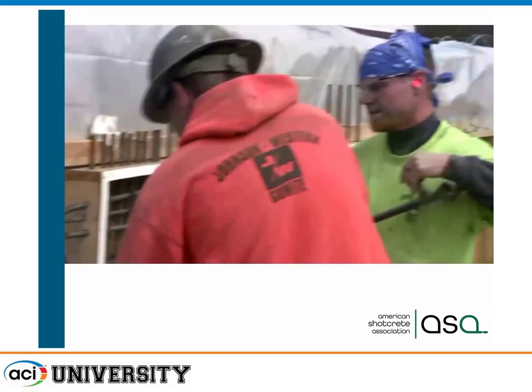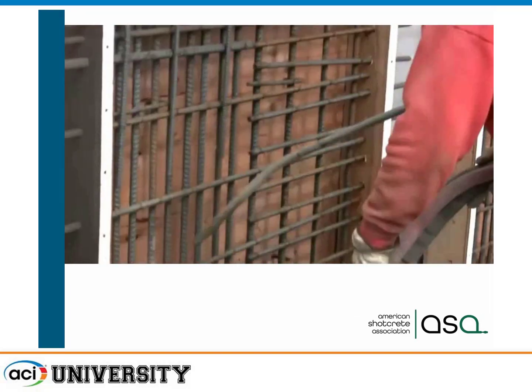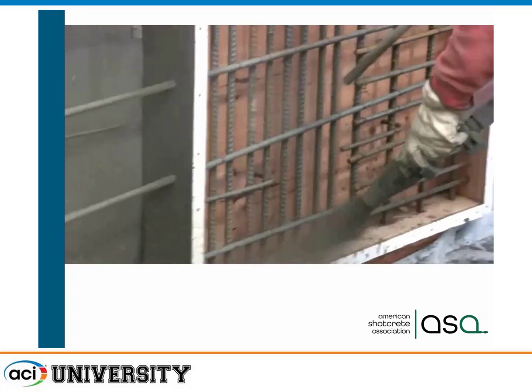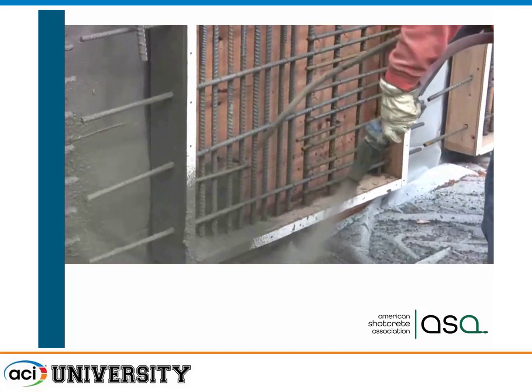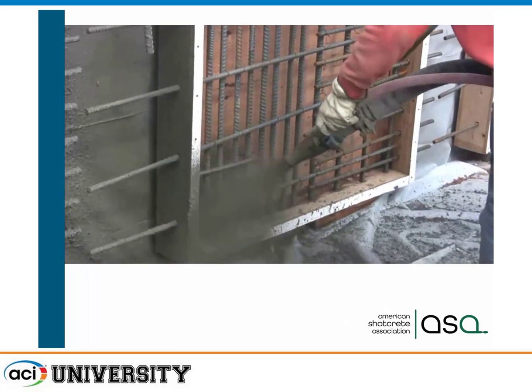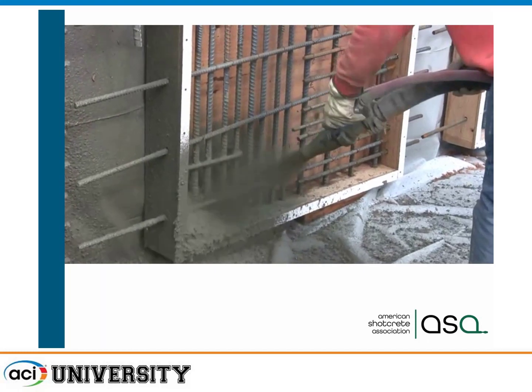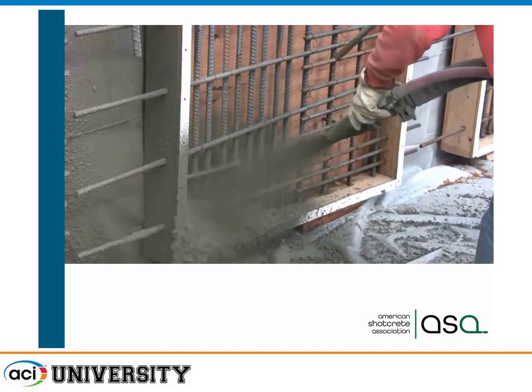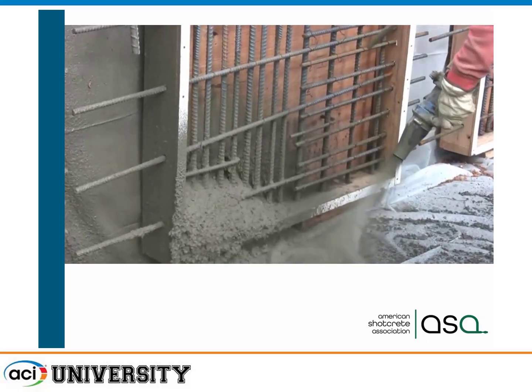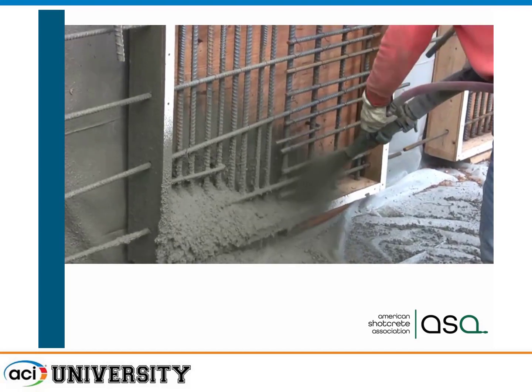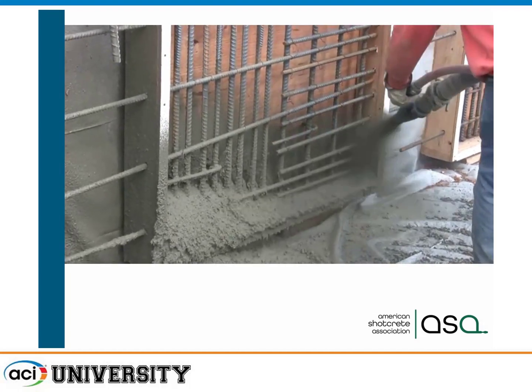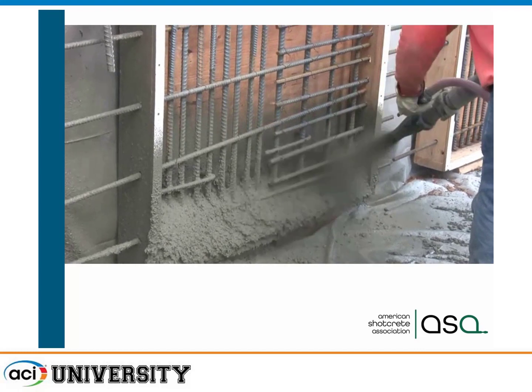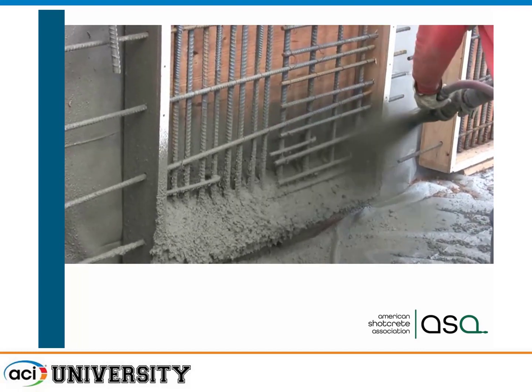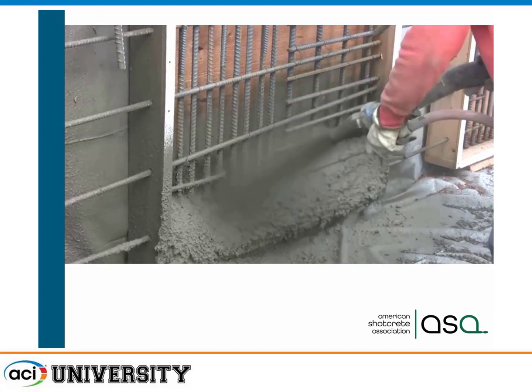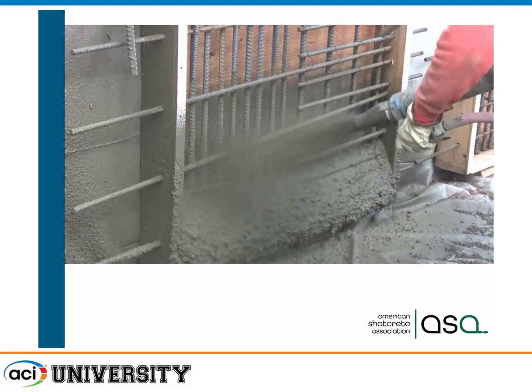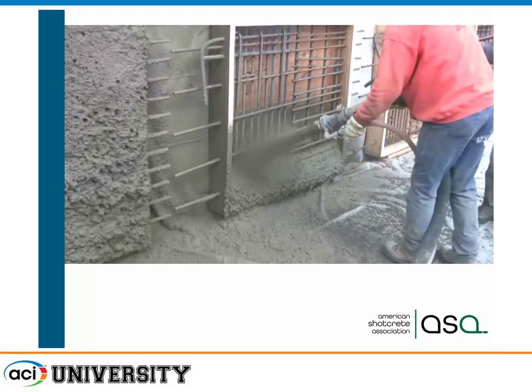I'm just showing this. This is a video of Shotcrete going in place. How many people have seen Shotcrete? Not everybody. But what we're doing is taking very low slump concrete, shooting it in place, basically making it no slump concrete to build vertical or overhead surfaces in place. This is wet mix. You can see the concrete going in place, fully encasing the rebar. We're able to visually see all the concrete going in place, so we know when we get good encasement of the rebars that we're getting full consolidation of the concrete.